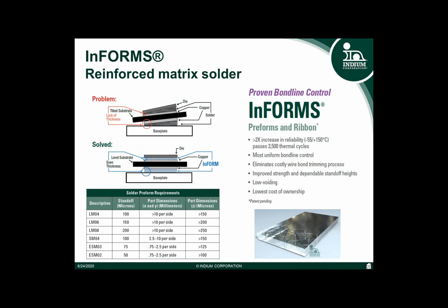So this could be in excess of 3,500 cycles, where the pass-fail criteria in aviation was as low as 1,000 cycles. So we're able to improve the reliability of this assembly, and in turn improve the reliability of the component or module in service as well.